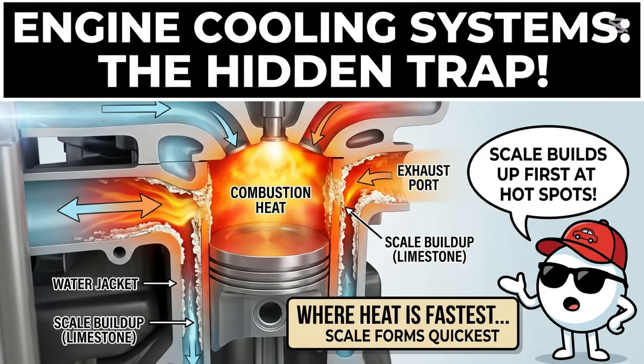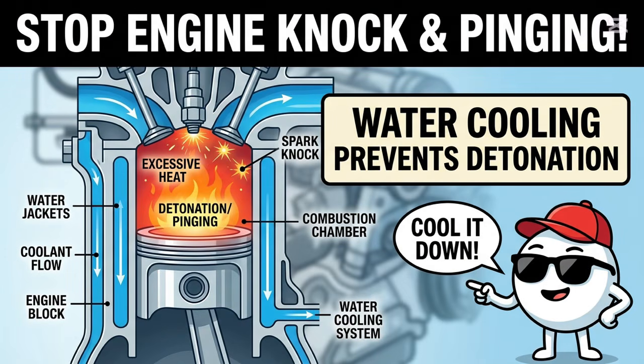And because heat transfer happens fastest at the cylinder walls and exhaust ports, the areas doing the most cooling work, that's exactly where scale forms fastest too. It's a cruel bit of physics. The parts of the engine that most need to stay clear and efficient are the parts getting coated first. Calcium carbonate scale is, unfortunately, an excellent thermal insulator, hundreds of times more resistant to heat transfer than raw aluminum or steel. Even a microscopic layer, something like 1/100th of an inch thick, can measurably reduce heat transfer efficiency, in some cases by as much as 40%. That trapped heat builds up inside the combustion chamber and can trigger chronic engine detonation, what most people know as spark knock or pinging, especially under heavy acceleration or load.